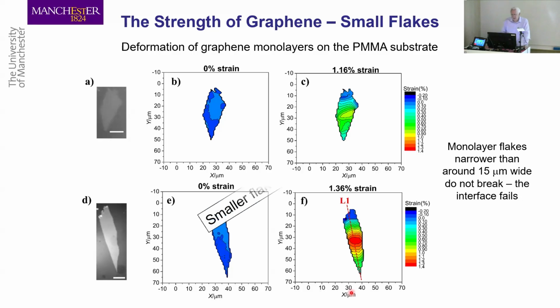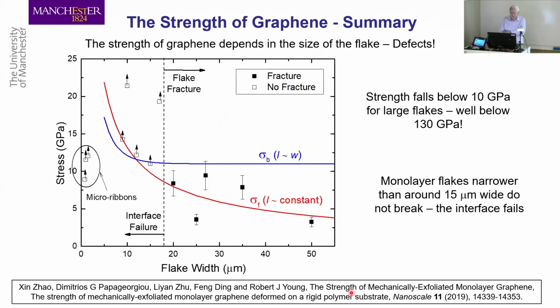And we looked at loads of flakes and found that these smaller straight flakes are stronger. And of course, that's something known, that small things are generally stronger than big things because of defects. And we've done a lot of analysis on that. And what we've done here is there's some measurements here from lots of flakes we've looked at. Well, this is the stress required to break the flake